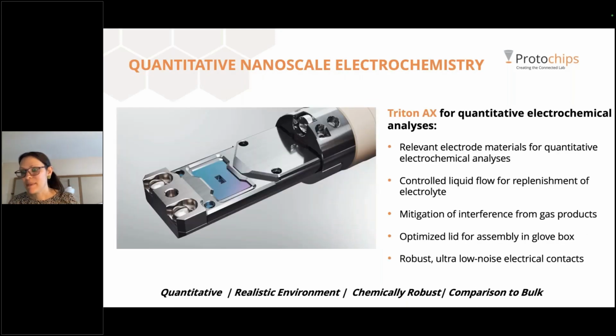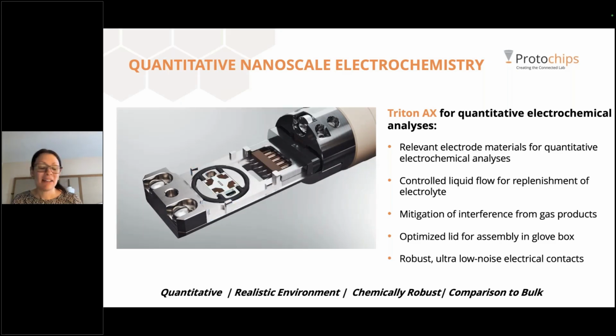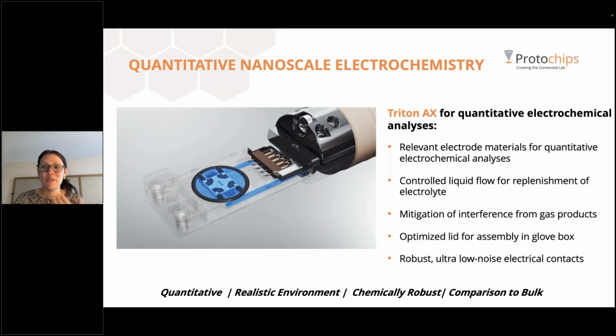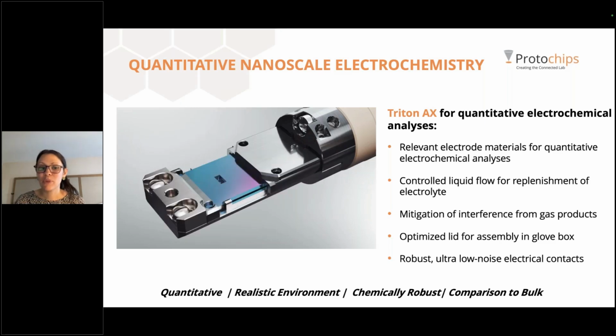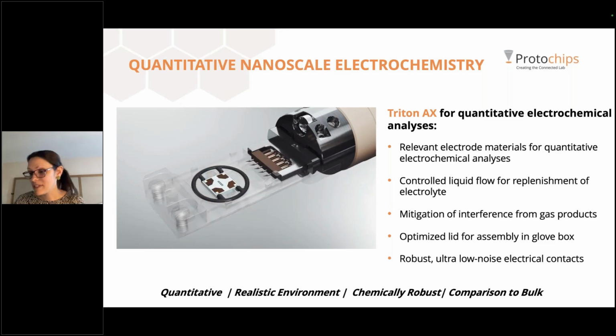Now, the first step in these types of experiments is to ensure the electrochemistry that you're obtaining is actually quantitative. If it's not quantitative, then the images and the story you have to tell don't really make a lot of sense. It needs to complement whatever bulk experiments that you would be using them with. And so in order to enable quantitative electrochemical analysis, we've ensured that you've got different electrode materials as options. So the working electrode can be carbon, glassy carbon, or platinum, which again, very comparable to what's used on the bulk scale.